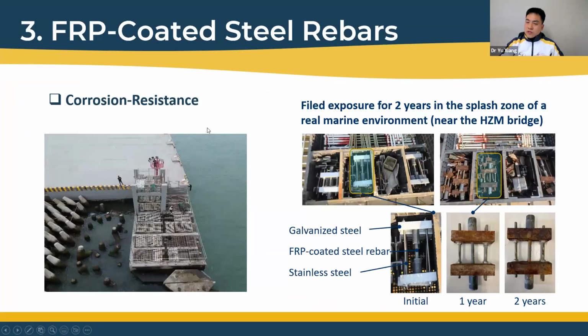In addition to the laboratory exposure, we also placed FRP coated steel rebars in a real marine environment near Hong Kong, at the west artificial island of the Hong Kong-Zhuhai-Macau Bridge. The exposure condition is the splash zone, a very harsh corrosive environment for metal as specified by existing exposure standards. We designed a special fixture to apply a pre-tension to the FRP coated steel rebar.